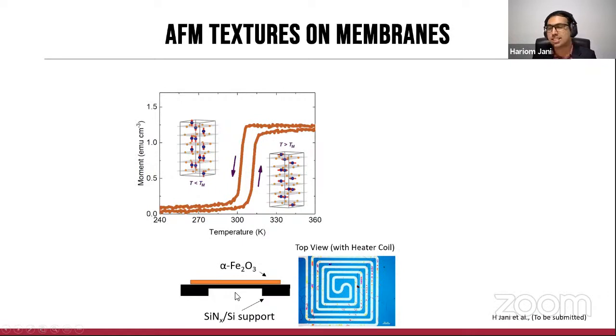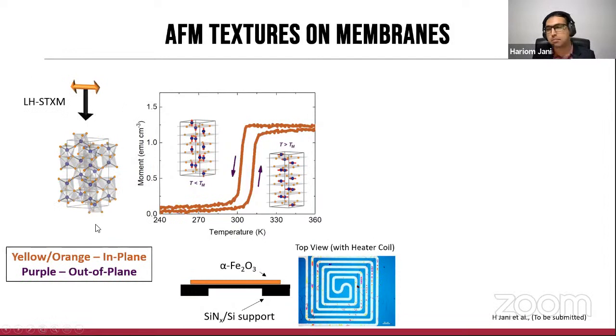This fundamentally was necessitated because we wanted to do experiments which allow in situ control, and this is not as easily possible in PEEM because of the electron optics that are present in the system here. But if you have X-ray transmission, a lot of in situ experiments can be done. And so this is done by STXM. And I've just shown a micrograph here of what it looks like. The intricate pattern shown here is actually a heater which is located on the system, and the image in the background is actually the Fe2O3 membrane, which is placed on top of the silicon nitride silicon holder.